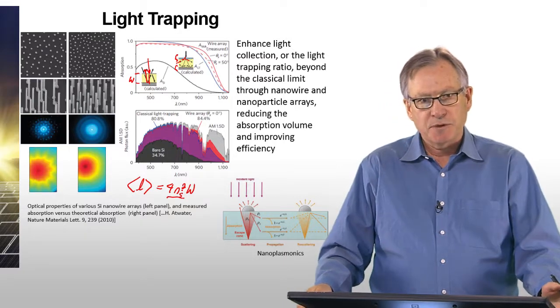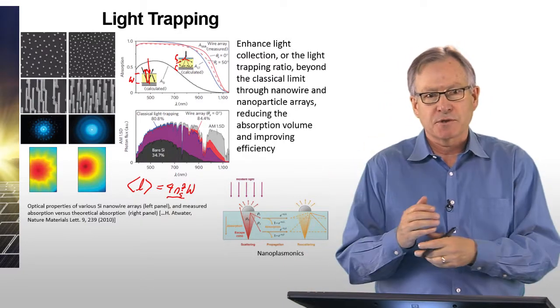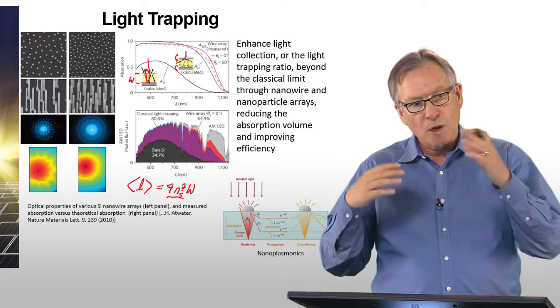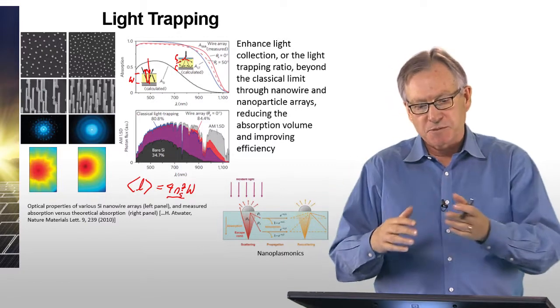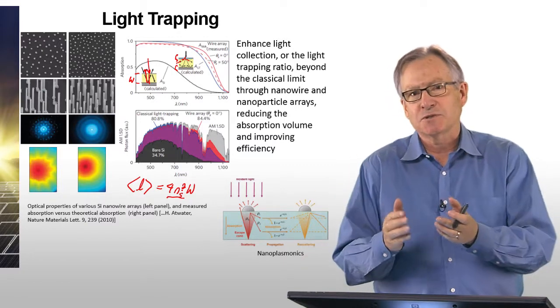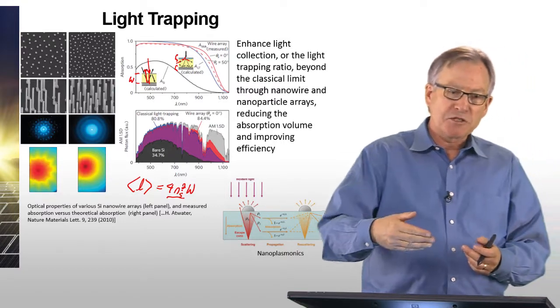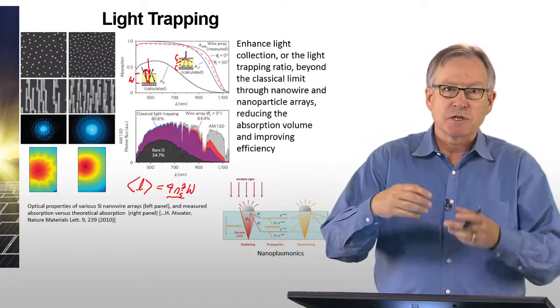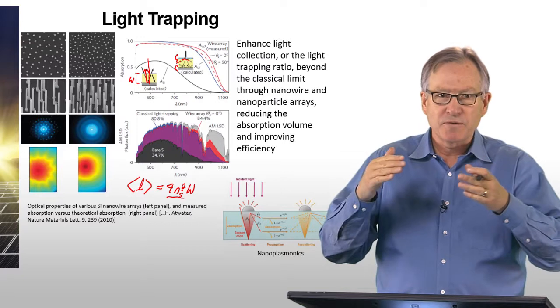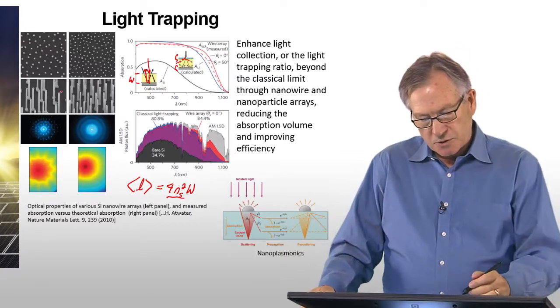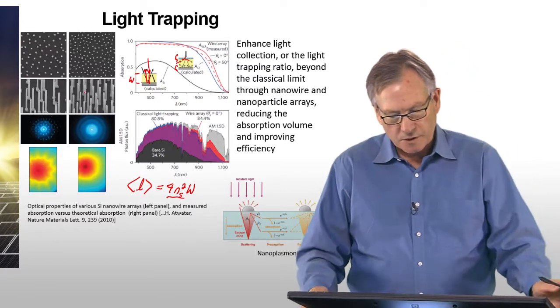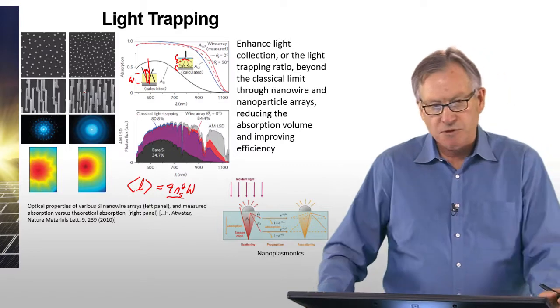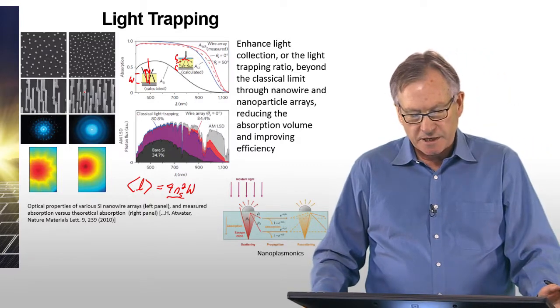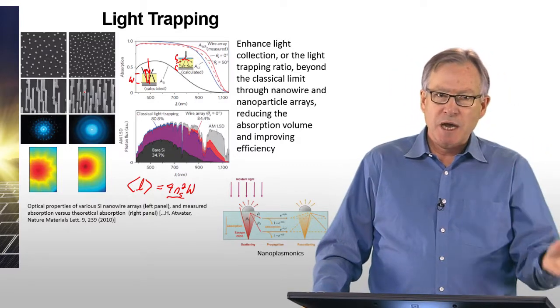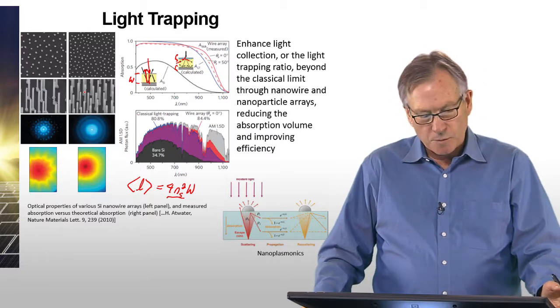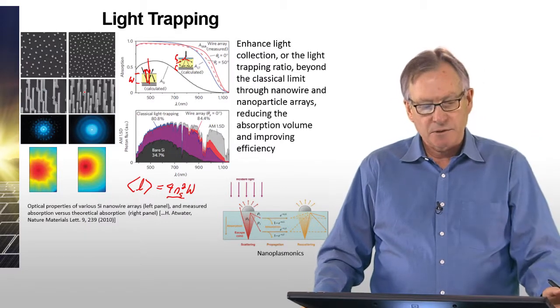And that means that you have to go beyond ray optics. You have to go to full wave optics, in which diffraction becomes important, and you need to look at structures that have characteristic dimensions and spacings that are much less than, say, the wavelength of the light. So what's shown here on the left is work that was done by Harry Atwater's group at Caltech, looking at enhancement of light trapping due to forming a forest or an array of nanowires.